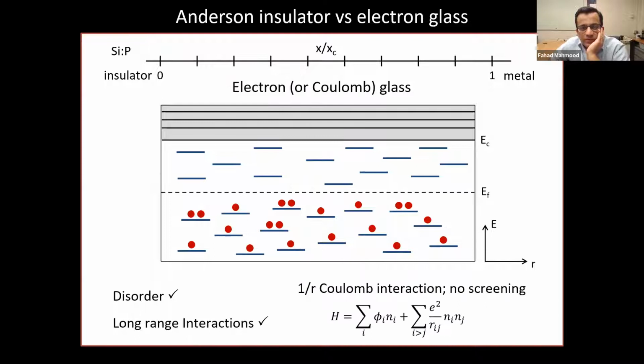What's interesting is when we introduce long-range interactions. Now your electrons are localized on each site. And here, the Coulomb interaction between electrons is truly long-range, because overall the system is still insulating, and so your screening is very weak. The long-range Coulomb interaction is not screened. So now this is a problem where you have disorder present and you have long-range interactions. This is the system that's been historically called an electron glass or a Coulomb glass.